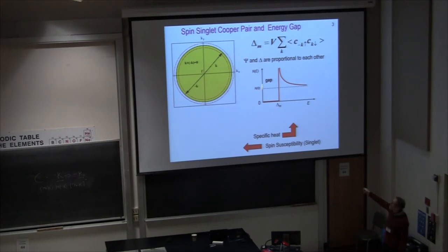And so you have this energy gap. Here is the density of states versus energy. In the normal Fermi sea, you have an approximately constant density of states, and so you have excitations everywhere. But once you form the superconductor, all the states up to the superconducting gap are fully gapped and so can't participate in thermodynamics. And then you get this characteristic square root singularity, because suddenly you can break Cooper pairs, and at the place you can break them, you have many, many states available. And this means that you can see the presence of this gap in certain characteristic behaviors. For example, in specific heat, what's important is you get this exponential Boltzmann-like behavior at very low temperatures.